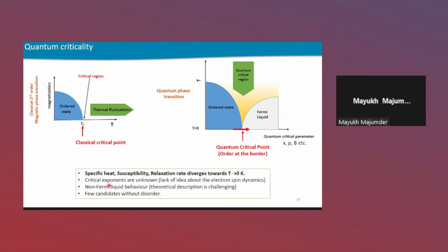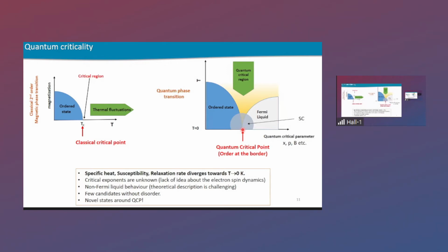And not only that, because of the presence of these critical fluctuations, you would expect some non-Fermi-liquid behavior. Okay, and of course, people have also seen that there are some systems where, because of the tuning, before reaching the quantum critical point, the system shows superconducting behavior as well. And those superconductors are mostly, or I would say all of them, unconventional superconductors because of the proximity to the magnetically ordered state. So these are the important aspects of studying quantum criticality.